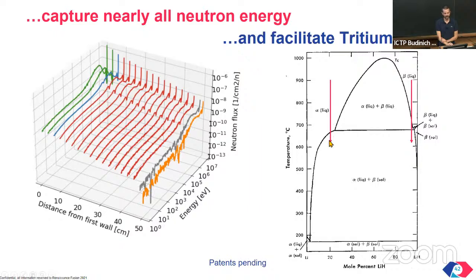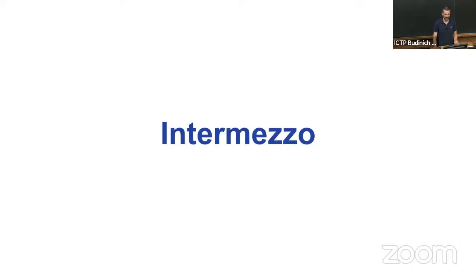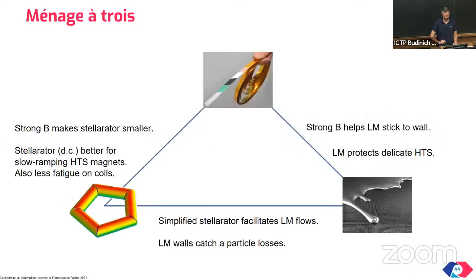Why? Because you make a phase transition to this phase here, where there is a precipitate rich in hydrides, including the tritide. And if you do it carefully, as a matter of fact, similar to a distillation, you can extract just the lithium tritide, because there are slight differences in precipitation of the hydrides.